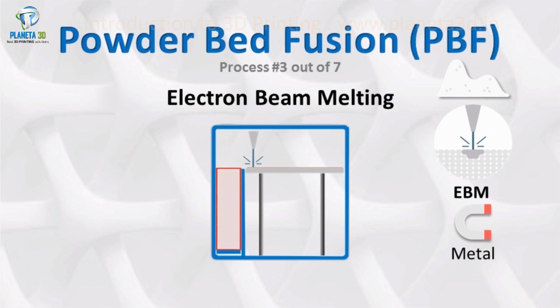EBM produces less residual stresses in parts, resulting in less distortion and less need for anchors and support structures. Moreover, EBM uses less energy and can produce layers at a faster rate than SLM and DMLS. But the minimum feature size, powder particle size, layer thickness, and surface finish are typically of lower quality. EBM also requires the parts to be produced in a vacuum, and the process can only be used with conductive materials.